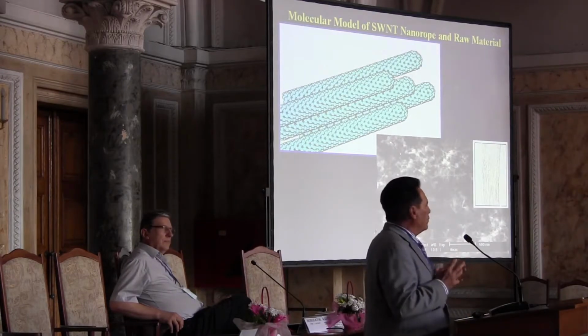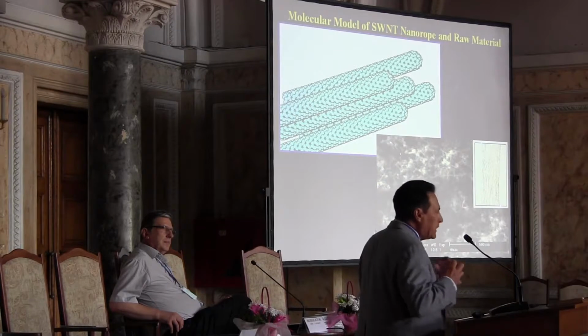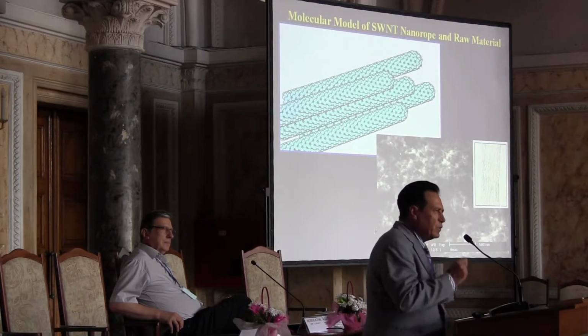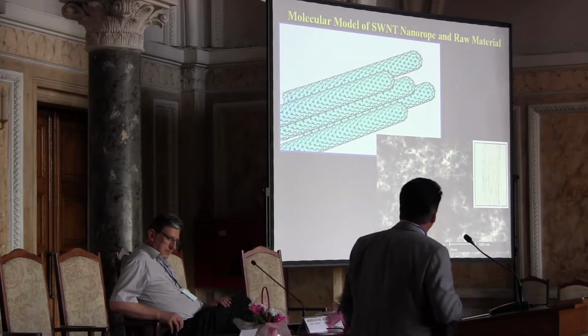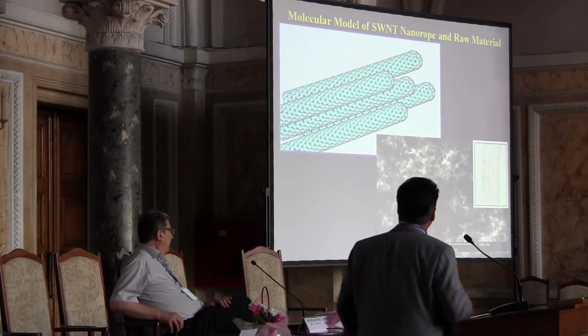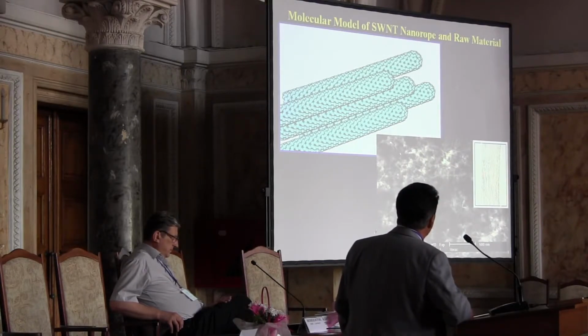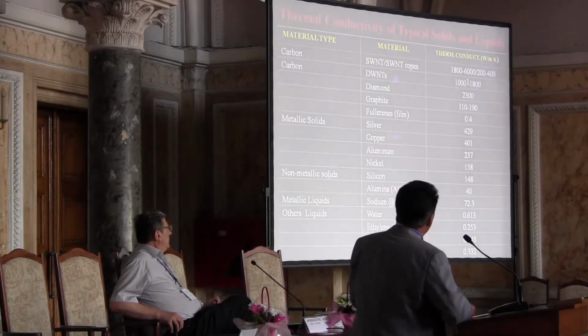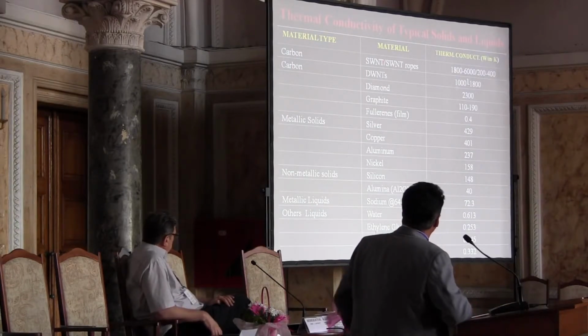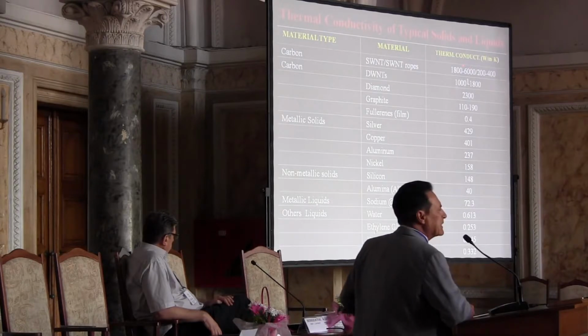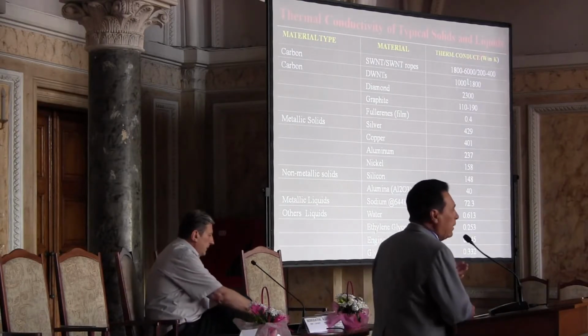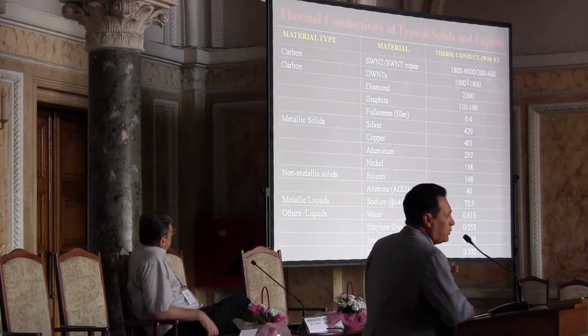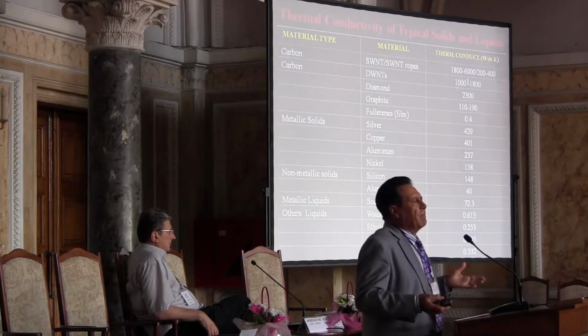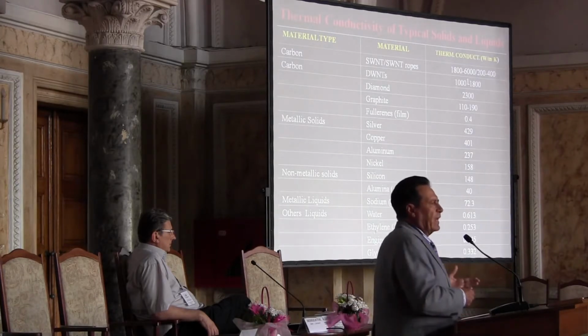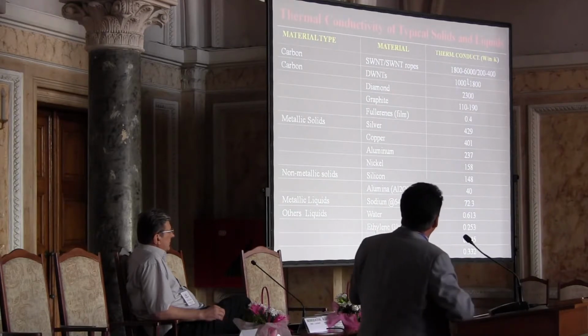These carbon nanotubes, as we have seen, are amazing materials, but they don't exist individually. What you have here is a model of a rope of carbon nanotubes. This is the conventional material. The thermal conductivity of an individual single wall nanotube can be of the order of 6,000 watts per meter Kelvin. But if you are dealing with multi-walls, that conductivity is between 200 and 400. So we don't have much benefit by integrating that material in a matrix, unless we go into the single walls.